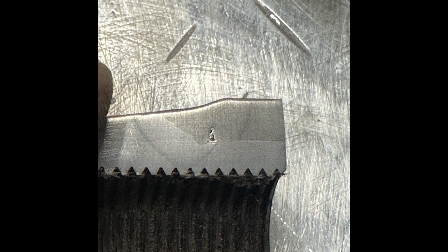Now, there's probably a couple reasons for that. The first thing I notice is that the penetration is actually down into the threaded insert quite a bit, actually. So my first thought on this is that my tungsten angle likely was going straight in and not angled at the tube as much as it should have. Therefore, it basically bridged over. So that's a tungsten issue for the angle.